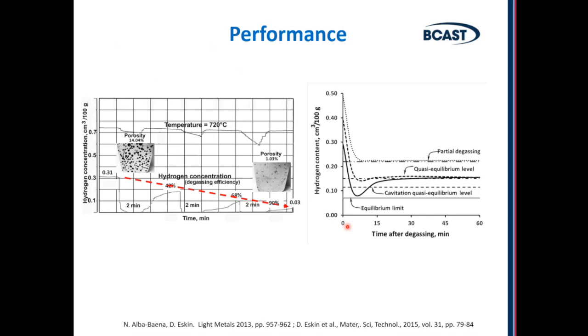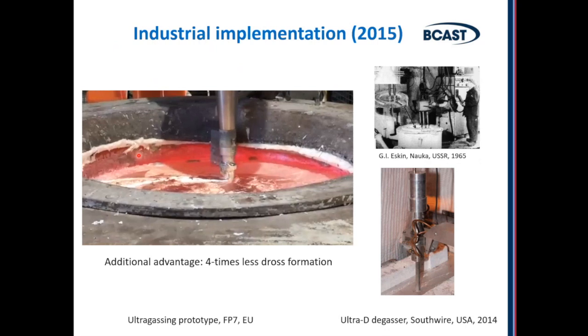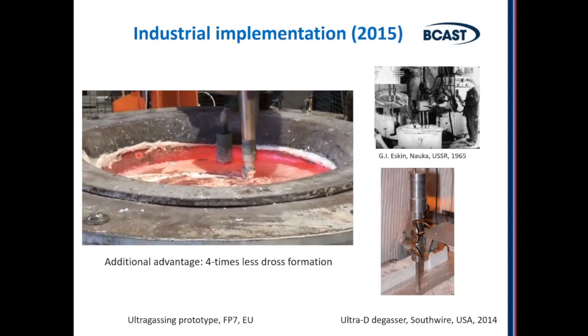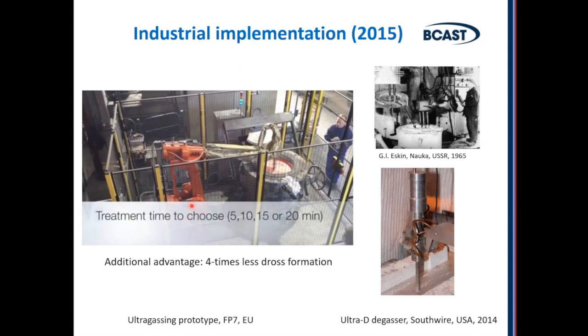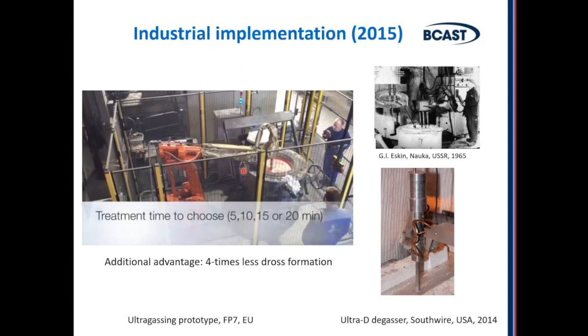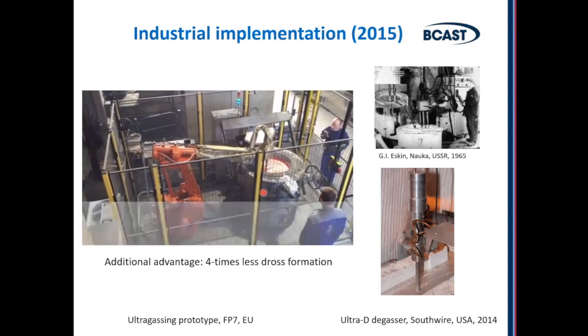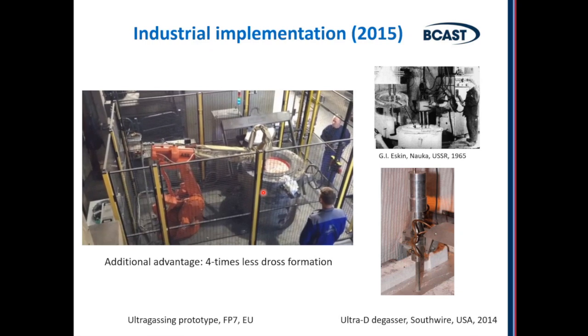And liquid aluminium can dissolve a lot of hydrogen. But solubility of hydrogen is very low in solid aluminium. So during solidification, if you don't extract hydrogen, you will have porosity, which you don't want, of course. So practical implementations of degassing. This is an example of a European project which we had a few years ago: ultrasonic degassing of roughly half ton of aluminium in foundry.